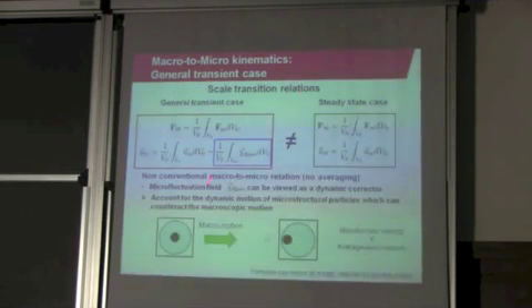Just for comparison, these are the scale transition relations in the quasi-static case. So the important thing here is this additional term. Now I do not require anymore that the volume average of the microscopic displacement should give me the macroscopic displacement, but there comes a correction term due to this dynamic microfluctuation. In fact, this dynamic microfluctuation can be seen as a sort of correlated fluctuation, as they would call it in statistical physics, while the static microfluctuation can be seen as a sort of statistical fluctuation. And that's what makes the whole difference here.